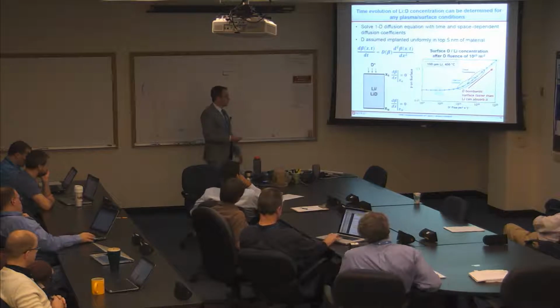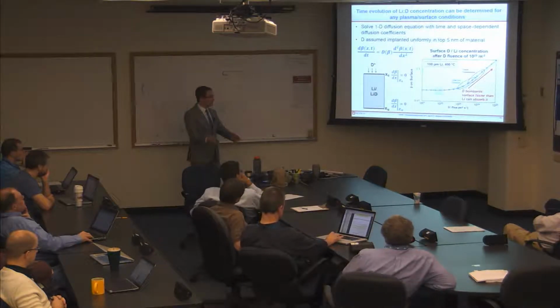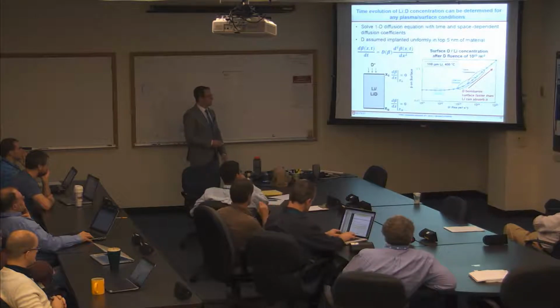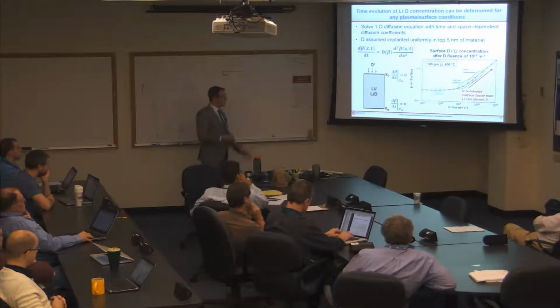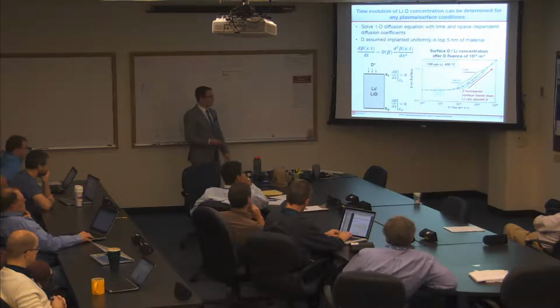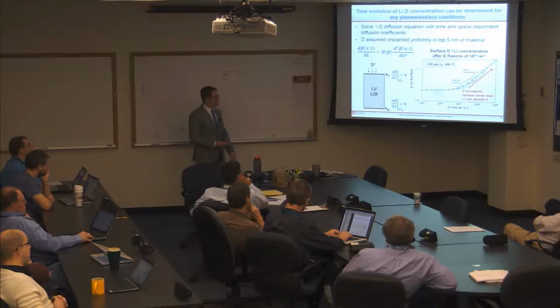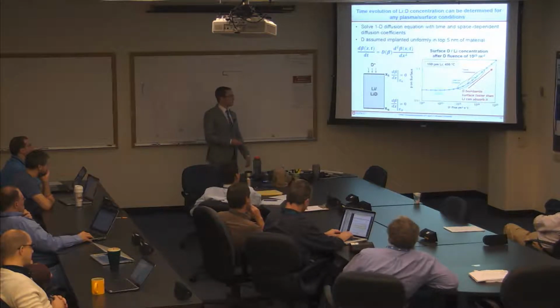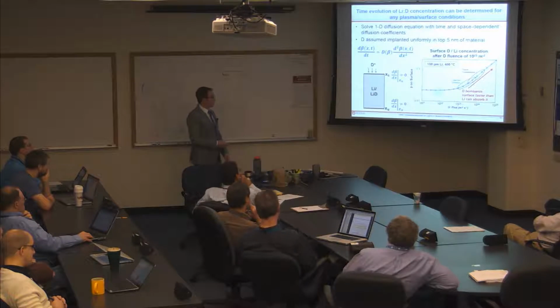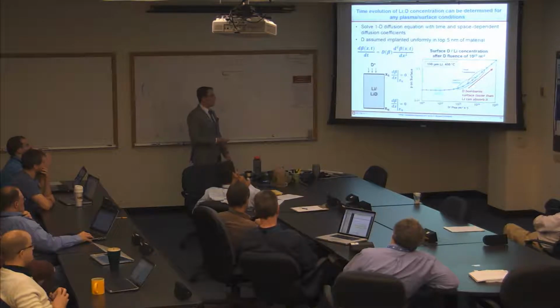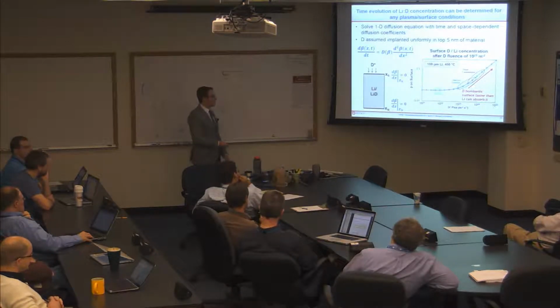of flux? At low fluxes, since the implantation is happening so slowly, the deuterium will just be readily absorbed by the lithium, and it'll establish a uniform concentration profile as a function of depth. But at very high fluxes, the deuterium actually begins to bombard the surface faster than the liquid lithium can absorb it without a runaway increase in the deuterium concentration. This was for a 100 micron thick lithium film at 400 C, at constant temperature. It's just a cartoon to demonstrate that you actually do get an enhancement of the saturation in real time as a function of the deuterium flux.